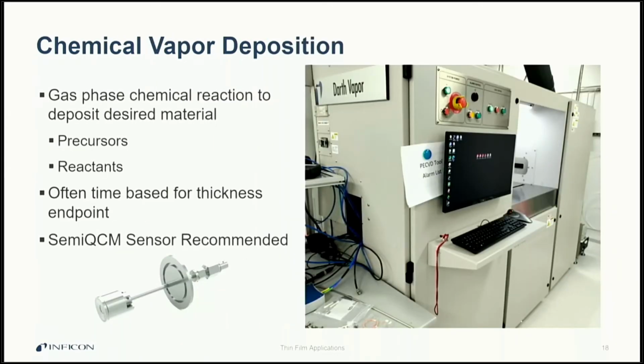Moving away from PVD applications, we take a look at chemical vapor deposition, or CVD. This is far different than the previous applications we've mentioned, as CVD goes about depositing the desired material onto the substrate through chemical reactions instead of physical changes. In these applications, precursors and other reactants are delivered to the chamber via inert carrier gases. The reactants and precursors then react on all surfaces of the chamber, depositing the desired material that previously was part of the precursor. CVD applications have a tendency to be very time-based, so long as the flow of gas into the chamber, as well as the concentration of precursors and reactants in the carrier gases, remains constant.